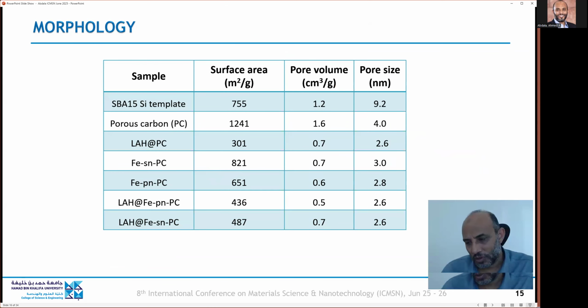The morphology and porosity were measured using BET. So the templated silica has 750 square meters per gram, porous carbon higher, surface area about 1,250. The pure metal hydride, when we supported it in porous carbon, is at about 300 square meters per gram. The metal catalyst is 650 to 820 square meters per gram, depending on the synthesis method. And then the metal hydride supported on or doped with the catalyst has a higher surface area than when we just supported it on porous carbon. So we get 440 to 490 square meters per gram.